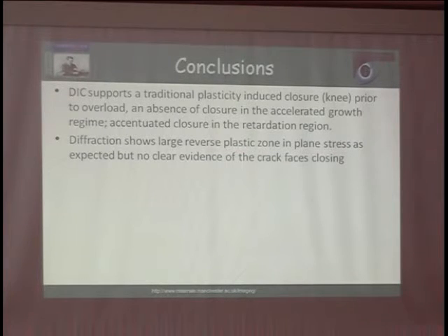Diffraction shows a very large reverse plastic zone in plane stress, but there's no clear evidence of crack face closing. What we don't see in any of our results is any significant compression along the crack faces. So we don't see the stresses that are set up when those crack faces come into contact. So that's an important question.